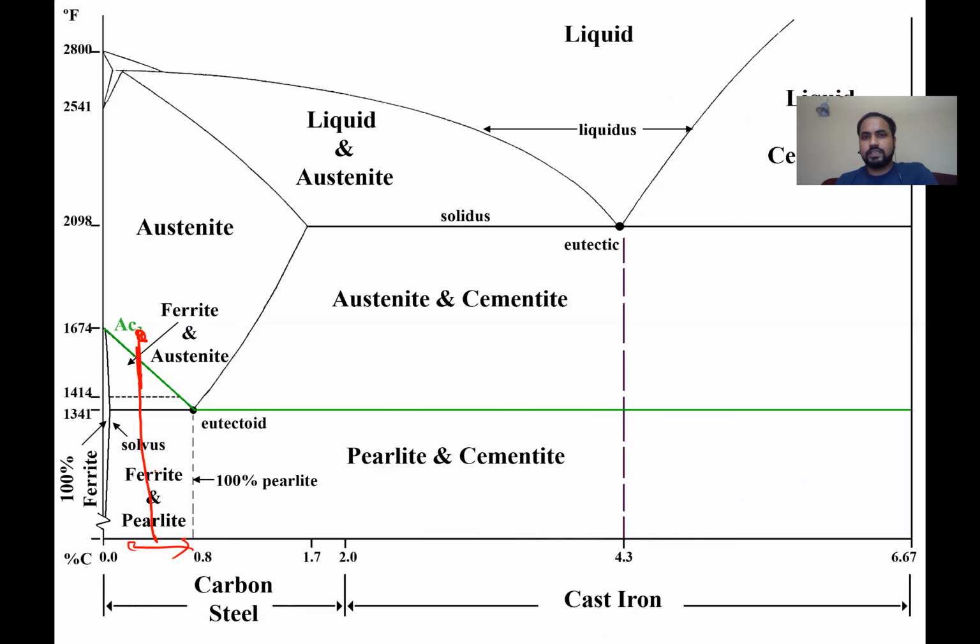The way I used to tell it in my class is just remember the A-M acronym, because A is austenite and you transform to martensite. So if you want to go to martensite, you have to transform everything to austenite. So the AC3 line becomes really important. If you're working with a high composition of carbon, then there's no way to get rid of cementite. So the AC3 line comes till here. As soon as you heat above this temperature, you get austenite and cementite, and then you do another kind of cooling process. So the AC3 line is one of the most important lines for heat treatment understanding.